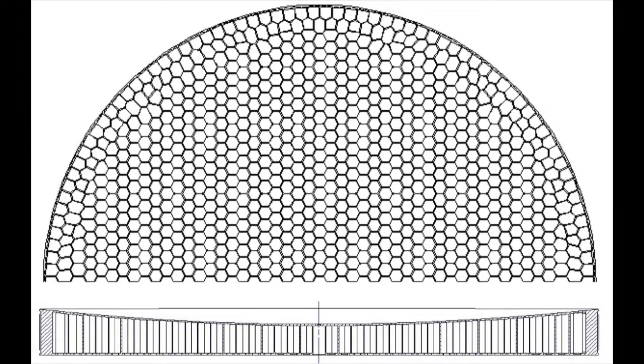What's the trick by which we make such large mirrors when it seemed impossible? For 30 or 40 years, no larger mirrors were made in the United States or anywhere in the world. These tricks all come from Roger Angel and the very clever scientists and engineers who work in the Mirror Lab at the Steward Observatory. The mirror is essentially a honeycomb, which means it's not a solid block of glass. The glass used is incidentally borosilicate, which is just a variant on common sand, so a very simple ingredient. The honeycomb mirror has a smooth and continuous faceplate of glass which is only 1 inch thick, but most of the volume of the mirror is a honeycomb where it's mostly air.